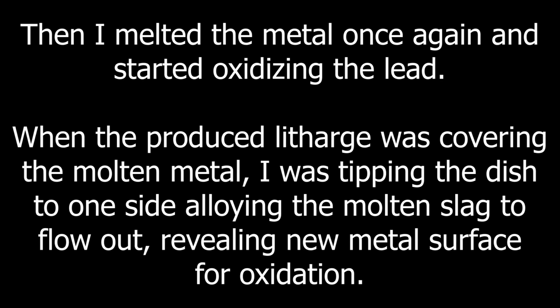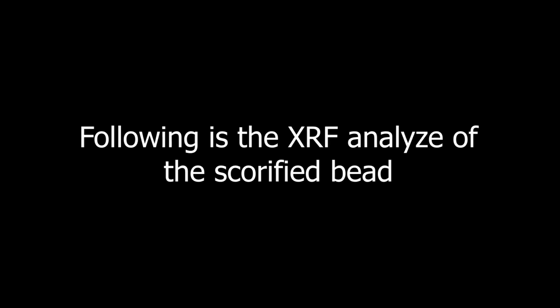Then I melted the metal once again and started oxidizing the lead. When the produced litharge was covering the molten metal, I was tipping the dish to one side, allowing the molten slag to flow out, revealing new metal surface for oxidation. This was repeated until the pool of molten metal stopped driving and froze into a solid bead. Following is the XRF analysis of the scorified bead.